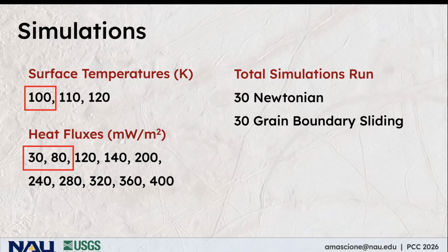For context, it's estimated that the surface temperature at Europa's equator, where Cilix is, is about 100 Kelvin. And while there's still much debate around the heat flux at Europa's surface, recent studies suggest that anywhere from 30 to 80 milliwatts per square meter is a reasonable assumption.